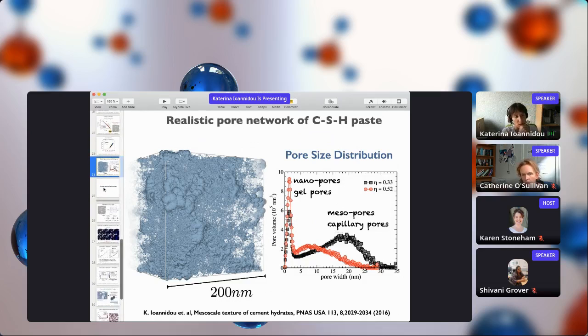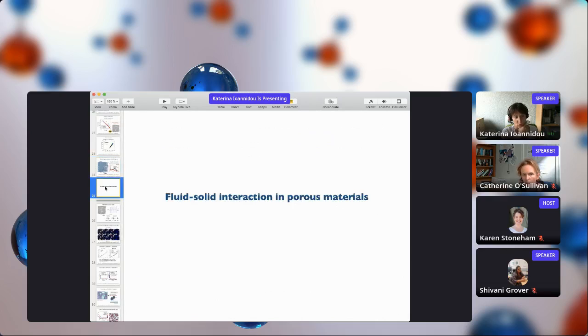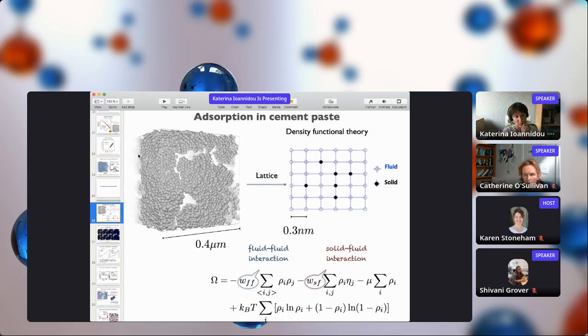On the third part of this talk, I wanted to show you a coarse-grained simulation for fluid-solid interaction, all connected again with cement. We started with this structure that I showed you for cement. This was a particle-based simulation using molecular dynamics and Monte Carlo, but now we are turning this simulation into a lattice to perform classical density functional theory. Each point in the lattice is either a solid or a fluid, and we have the interaction between a node that is fluid-fluid or solid-fluid. The solid-fluid interaction, in this case, we have calibrated from atomistic simulations.